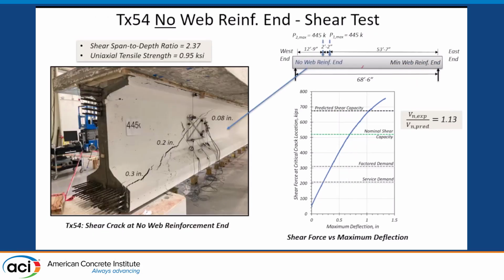So when we had the case with no web reinforcement at the end, it is also similar that we're reaching close to 800 kips. We're missing a little bit of shear reinforcement, so we didn't get quite up to that same value. But I think you'll see that the crack looks a little bit more dramatic there, and I can tell you from being in the lab when it was being tested that it doesn't give you as much ductility when you do not have the shear reinforcement.